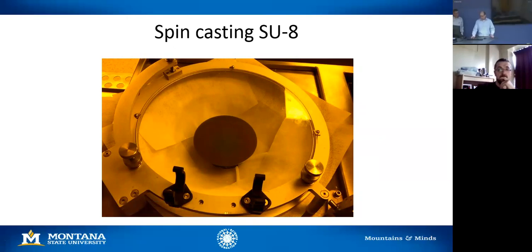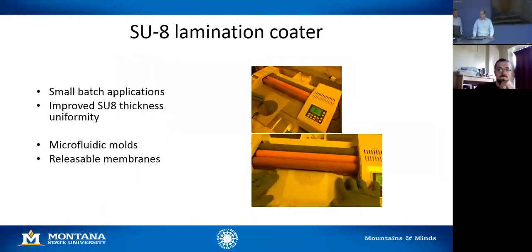Because of that, we have recently implemented an SU8 lamination system. In the last couple of years, companies have started selling commercially films of this type of negative epoxy already made, pressed into a laminate material, so it's not in solution anymore. You can put your wafer in and laminate this layer of film on top of it. The uniformity is much better from their manufacturing process, and it also gives you much better results when you're doing tenting, which is basically covering over already structured features where you have big holes, vias or voids. You can put this material over the top of that and start building three-dimensional structures with much bigger spatial features than you could otherwise by spin casting.